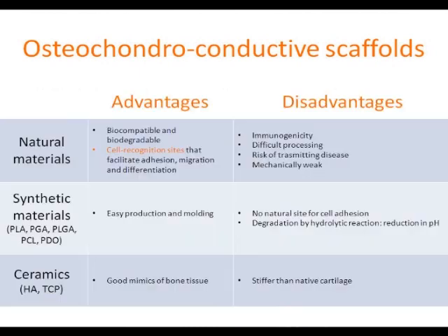And we have natural materials, synthetic materials, and ceramics, with advantages and disadvantages. The synthetic materials, like the reabsorbable one, they can cause degradation reaction into the body. So sometimes I have patients with a lot of wear and bone lysis due to the degradation byproducts of this material, or for a particular reaction to this material. So it's not easy to decide what to use.